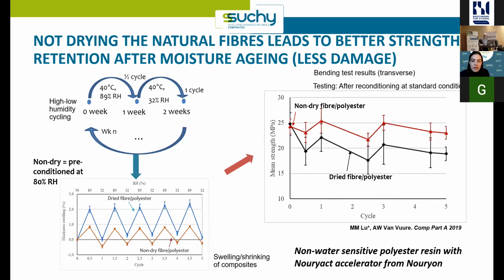And then in the first study on polyester resin, this was already published in Composites Part A, we actually preconditioned the fibers at 80% humidity, so quite nicely swollen fibers. And then we did cyclic loading up to high humidity 89 and then low humidity 32, corresponding to conditions that you will have in reality. And indeed, we saw here, in blue is when you use fully dried fiber, and in red when it was already pre-swollen. Then we have less change in the dimensions of the composite over these moisture cycling events that we undergo.